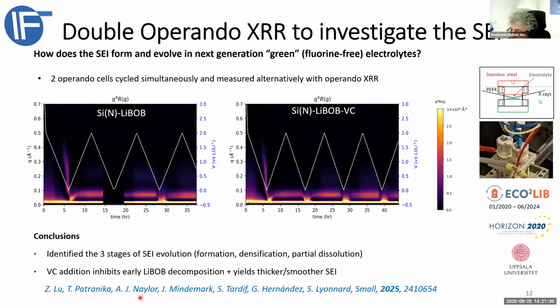So these teams have studied operando during cycling, charging and discharging. They have been able to measure the reflectivity as a function of time and of the voltage, or the current. And they were able to look at the formation, or not, of the solid electrolyte interface between the electrolyte and the electrode. And it was a good measure to clearly reveal that this additive inhibits the decomposition of the electrolyte, which was very good information to obtain from this technique.